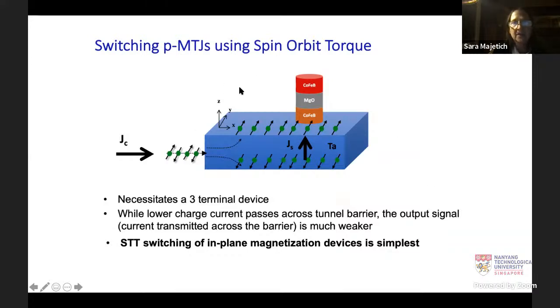Again, I mentioned spin orbit torque as a possibility. The last results I was showing were based on spin transfer torque. But the reason that we don't use spin orbit torque is that we need a 3-terminal device in that case, and that just makes the wiring a little bit more complicated.